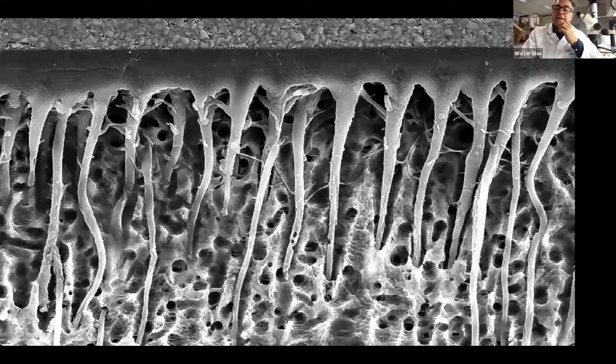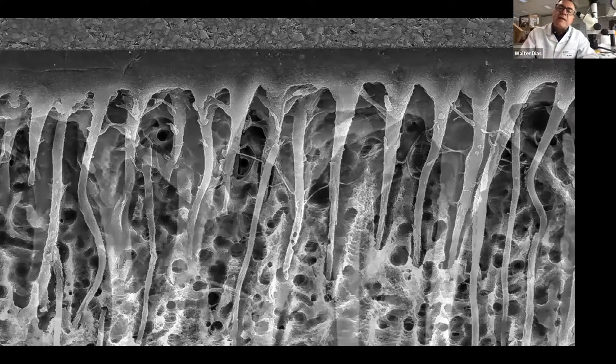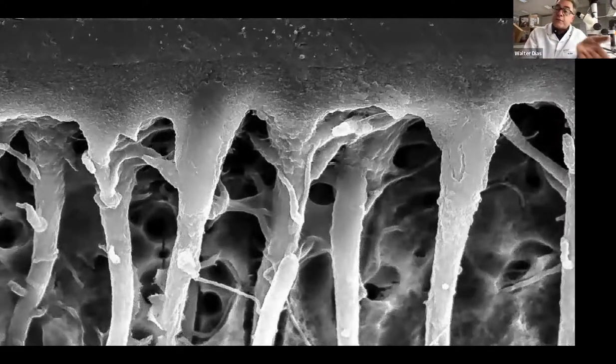You can see that these adhesives can penetrate very, very deep into the dentin. This adhesive that I'm showing you is Prime&Bond Active. You can see that I etched the dentin in this case because it's universal. I was checking for both etching modes. So in this case, I etched the dentin, and you can see how huge it is.